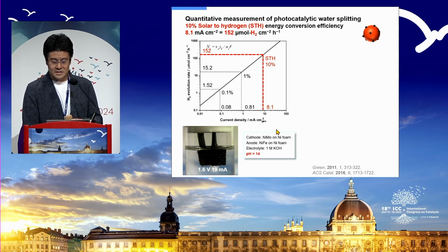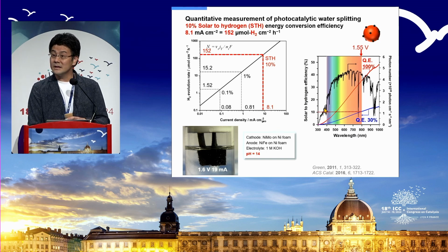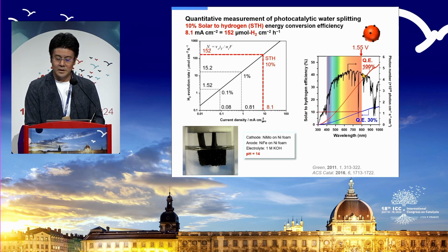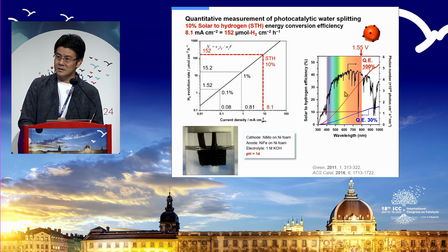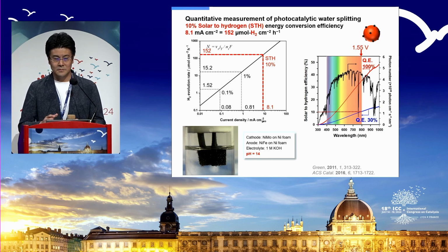So this 1.6 volt can be translated to visible light responsive, in the border between visible light and infrared light. So you cannot do this because you need a completely black electrode. You need to have a semi-transparent one. So you have to use somewhere around 600 nanometer. That is also reasonable in terms of band gap and the additional overall potential required.